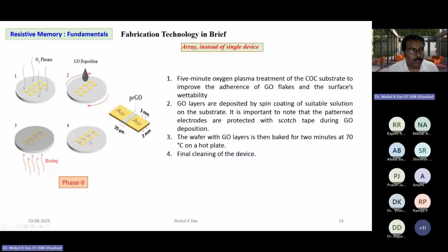Oxygen plasma: first you have to insert a mask on these, because otherwise oxygen plasma will hit the gold portions also. Oxygen plasma is generally applied to increase the wettability or adhesion force of oxide flakes, because if we put graphene oxide or any other oxide, the surface should be oxygen plasma treated. Then you put a drop of the proper solution for a particular oxide and spin coat it, so this coating of graphene oxide will be everywhere except on this portion. Then if you make some annealing, except for this gold portion, some graphene oxide will be deposited in between. And so finally you can see the picture.